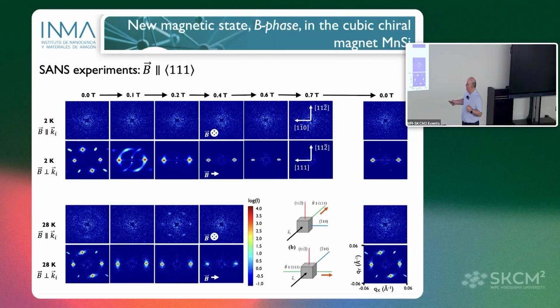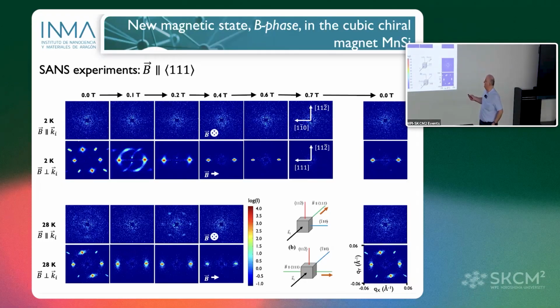But for this orientation, we were able to observe this. These points are multiple scattering of these 2. What does that mean? That at low temperature and zero magnetic field, our system develops helicoidal domains aligned along the main diagonals. If you don't apply magnetic field, your manganese silicide has 4 different helices propagating along the 4 main diagonals. When you increase a little bit the magnetic field, this point is going back here, and this is going there. That means that you are reorienting the magnetic domains toward the 111 direction in which you are applying the magnetic field.